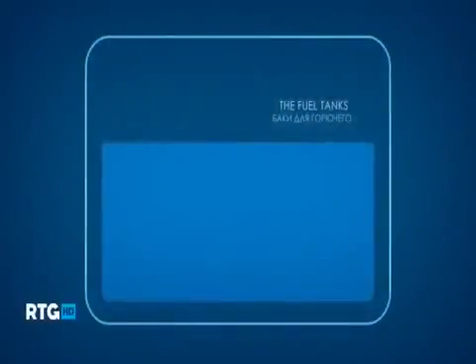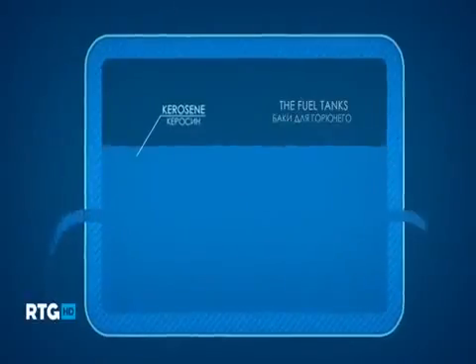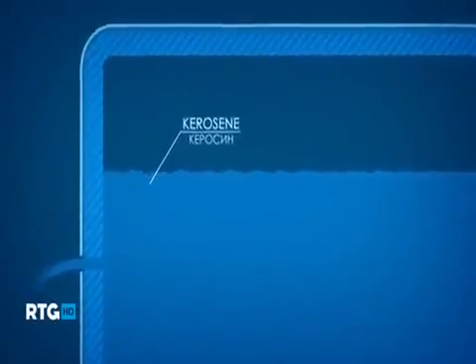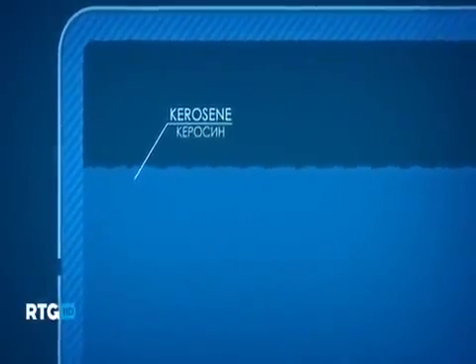The fuel tanks have a special construction. They're made of rubber with a protector. They're covered on the outside with a substance which reacts with kerosene to vulcanize the rubber. So, if the tank is pierced, the kerosene that leaks out will cause a chemical reaction that will block the hole. This system stops fuel from leaking for 6 to 8 hours.